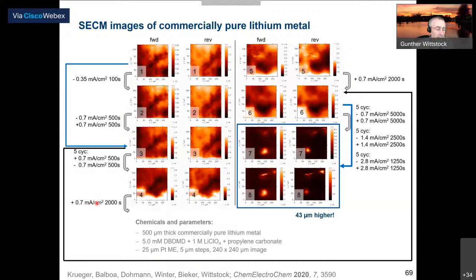Then we made it for longer time to pass more charge, then for even longer time, and then we increased the current density. And then you see, okay, the surface is not changing too much. And then if we go to too high charges, then we slowly start to see changes.